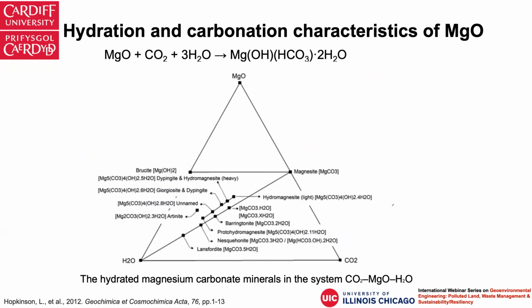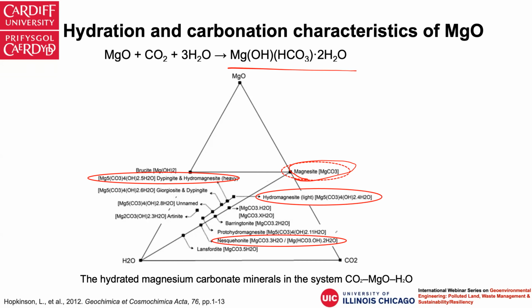And if you subject magnesia to carbon dioxide, at high concentration, you produce various kinds of hydrated magnesium carbonates. Thermodynamically, the most stable phase is magnesite. It should go back to magnesite. But in reality, this reaction is kinetically hindered. So in most cases, you won't get magnesite directly. You actually get nesquehonite, hydromagnesite or dypingite. So these are different kinds of hydrated magnesium carbonates.